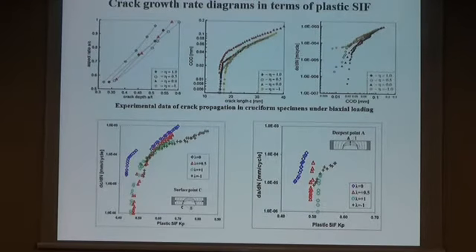So, as a result, the crack growth rate on the free surface of the specimen and crack growth rate in the deepest point were presented in terms of plastic stress intensity factor. And I would like to draw your attention to the fact that in the first stage of the fracture process in cruciform specimen, crack growth rate significantly increases in a small range of plastic stress intensity factors. And in the next stage, a significant reduction of crack growth rate is observed, and crack growth occurs in a wide range of plastic stress intensity factor.